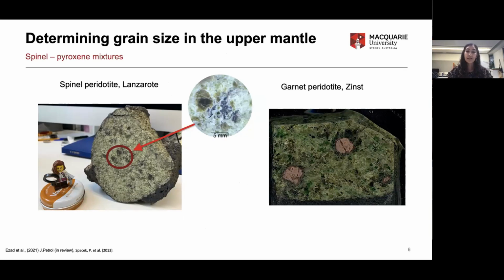And garnet peridotites often break down into spinel and orthopyroxene mixtures, which is what you can see here on the left-hand side. This intergrowth is essentially a resetting of grain size, because as this garnet breaks down, it forms spinel and orthopyroxene nuclei. Over time, these will grow and coarsen. And if we can pick up a spinel peridotite on the surface of the planet and measure the grain size of these spinel and orthopyroxene mixtures, we might be able to say something about pressure, temperature, and time pathways, or even residence times within the spinel peridotite zone. So that's where I became really interested in seeing whether I could try and constrain some of these grain growth kinetics in the upper mantle.